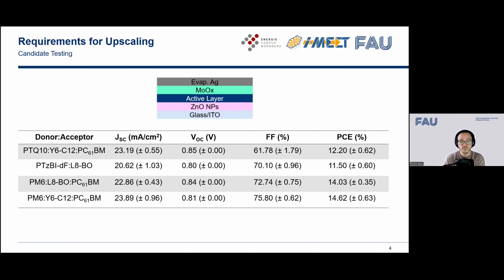So if we then move to PM6 as the donor polymer and combine it with L8BO, we can see an increase in JSC and maintain the high fill factors.